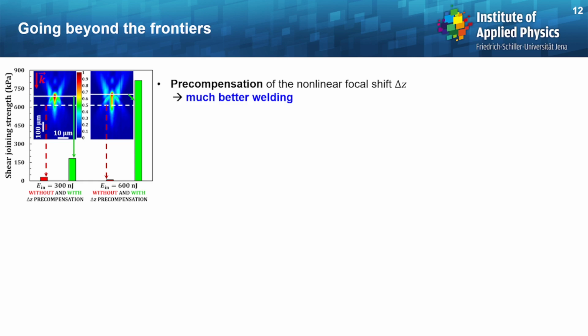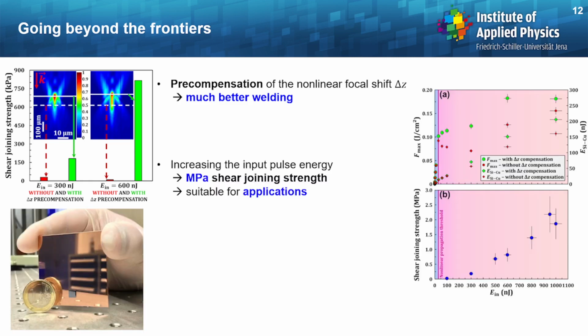Okay, so what now if we keep this delta Z precompensation strategy and at the same time increase the input pulse energy? Well, the results are shown here in terms of shear joining strength as a function of the input pulse energy, where you can see that it is possible to reach around 2 megapascal for approximately 1 microjoule input pulse energy. And this is suitable for applications, and this can be easily explained by the maximum fluence at the interface as well as the energy reaching the interface, which is much higher when you precompensate for the nonlinear focal shift.